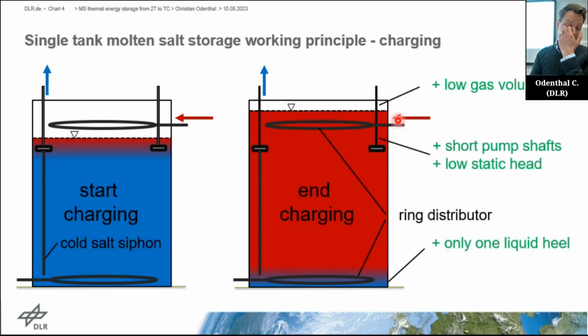There are some advantages of this concept. The first one is with the two tanks, you have obviously about 50% of the volume unused. You have a high volume of gases, which you have to manage. And in that case, this volume is clearly reduced. Another aspect is in the two-tank system, you always have to completely empty the tanks. So the pumps need to have very long shafts. And in this case, since you always have some liquid level in here, you can use short shafted pumps, which are much less costly.